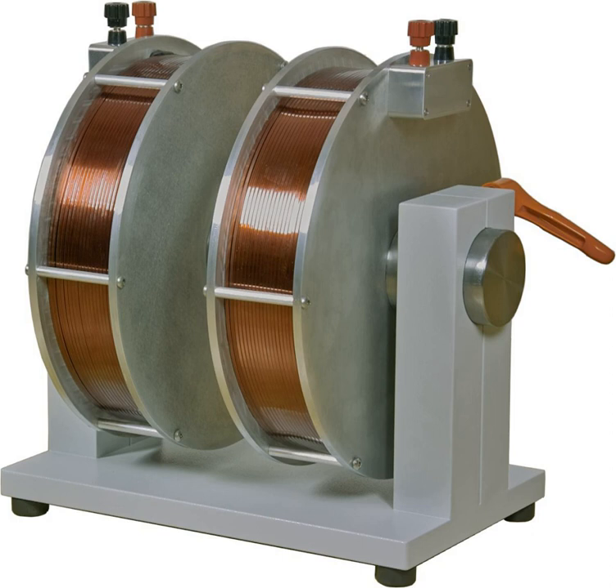Superconducting magnets are limited by the field strength at which a winding material ceases to be superconducting. Current designs are limited to 10 to 20 T, with the current 2017 record of 32 T. The necessary refrigeration equipment and cryostat make them much more expensive than ordinary electromagnets. However, in high-power applications this can be offset by lower operating costs, since after startup no power is required for the windings, since no energy is lost to ohmic heating. They are used in particle accelerators and MRI machines.